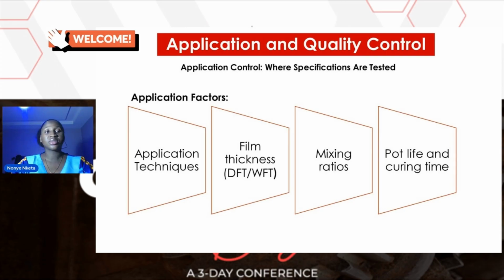So application techniques, setting your spray gun, the pressure and all of that. Then film thickness, a lot of people don't even care. What they know is do one pass, do two passes. So you need to be sure that you're getting the required wet film thickness that will give you the specified DFT at the end of the day. Then mixing ratio, very, very important. Then pot life and curing time. All of this information is usually given on the specification data sheets or product data sheets or technical data sheets, depending on what the company calls it. So all of these are very important while you're preparing your coatings to actually do well on your substrate, to actually protect your substrate. And as you're doing this, you also need to check for quality and be sure that you are conforming to what is expected.